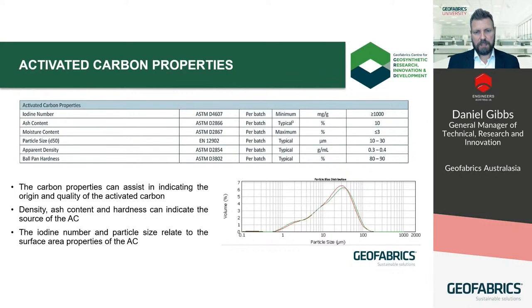Other than that, the other properties are really there to tell a story about the origins and, to some extent, the quality of the activated carbon. For example, low ash, which is around 3 to 5, can indicate coconut shell activated carbon, but it's also indicative of acid-washed coal-based carbon. Coconut shell is harder, in the order of 98 to 99, and more dense than coal, ranging from 0.4 to around 0.54. So if you look at the combination of hardness, ash, and density, you can use this to determine the origin.